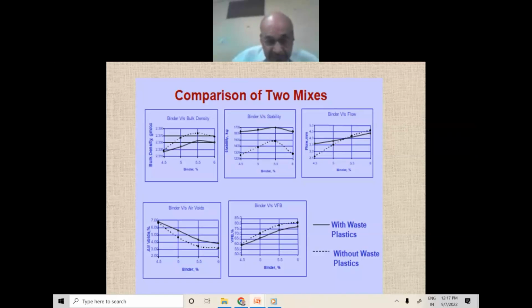Then optimum bitumen content shall be determined by plotting the graphs of unit weight versus bitumen content, Marshall stability versus bitumen content, voids in mix versus bitumen content, aggregate voids filled with bitumen versus bitumen content, and flow value versus bitumen content. These are the plots. Now we will see the difference.